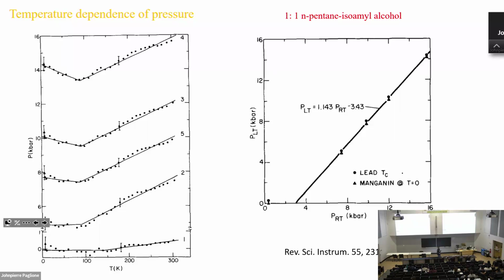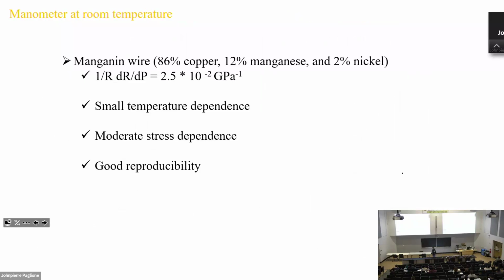Now, since we know the pressure will change, you better know the exact pressure. The way we know the pressure, we typically put in two pressure gauges. One is this manganin wire. This works well for room temperature. So basically, the resistivity will change as a function of pressure. And if you calculate this, the change is actually pretty sizable. But this doesn't work well for low temperature.